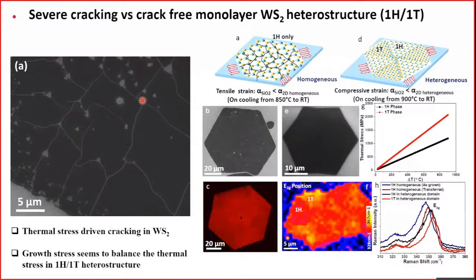All these voids are connected by cracks, which means that after the CVD growth or during the cooling process, your 2D material is no longer intact, rather it is severely fractured. The point defects and the voids are acting as the culprit for the fracture. At the same time, the thermal mismatch stress between the substrate and your 2D material is imposing thermal stress. What we found, interestingly, is that this kind of fracture happens when we have a 1H phase.